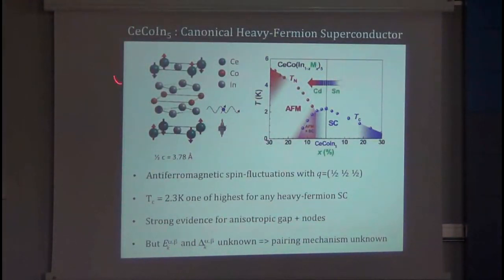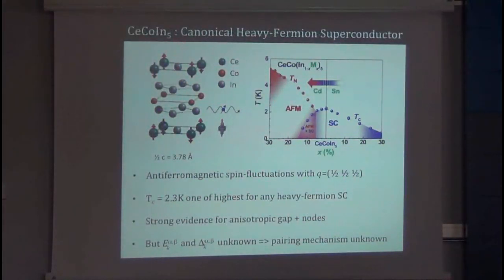Okay, back to cerium, cobalt, indium 5. So we had to do this to learn how to look for the heavy bands, because they're the basis of the superconductivity. But now we went to cerium, cobalt, indium 5. It's antiferromagnetic in its parent state. It's got a high TC. And our job is to measure the heavy band structure and the gap structure.